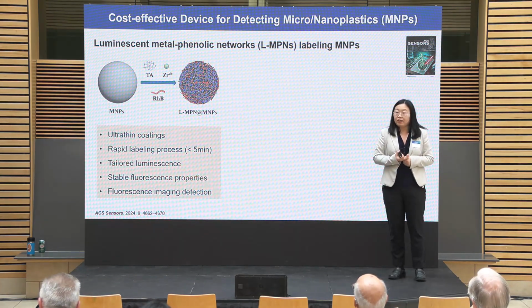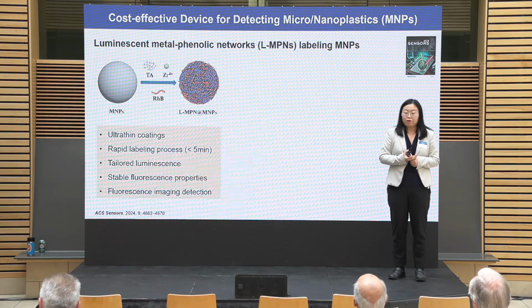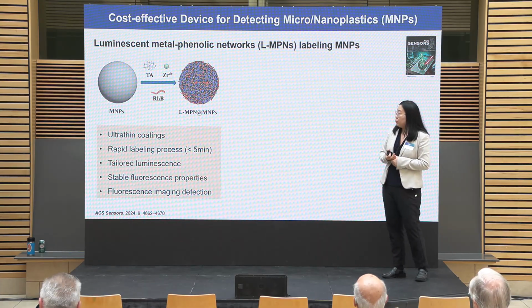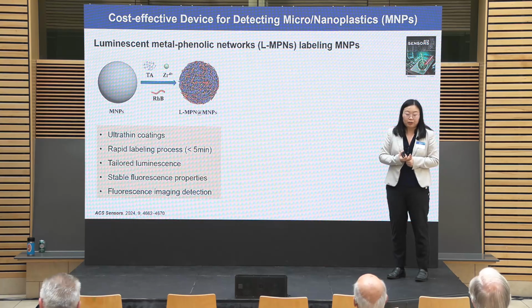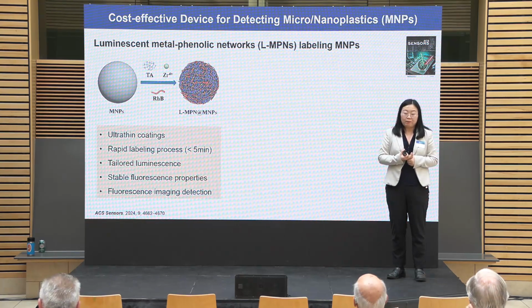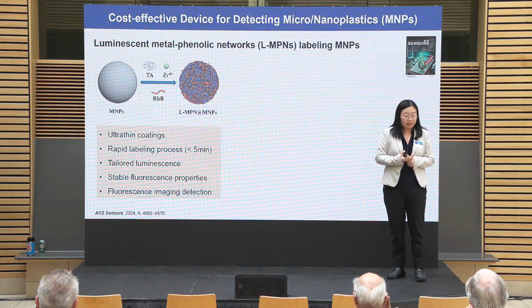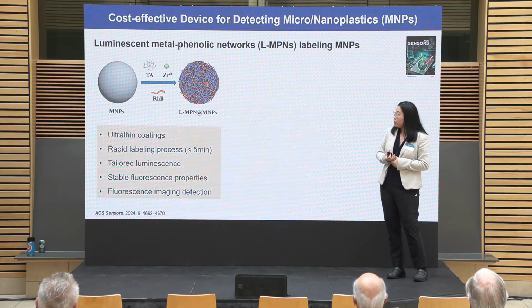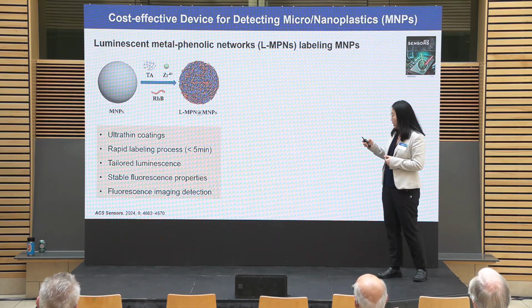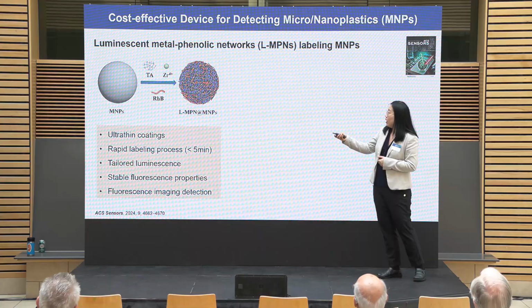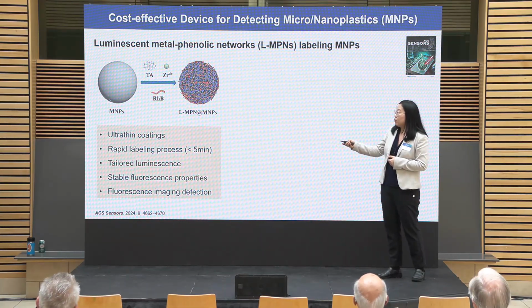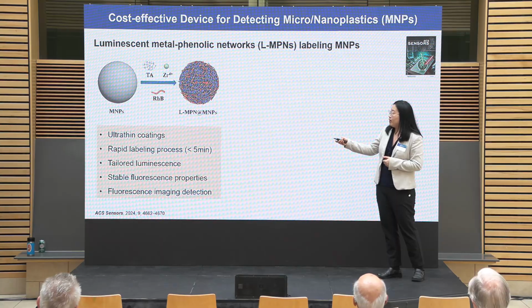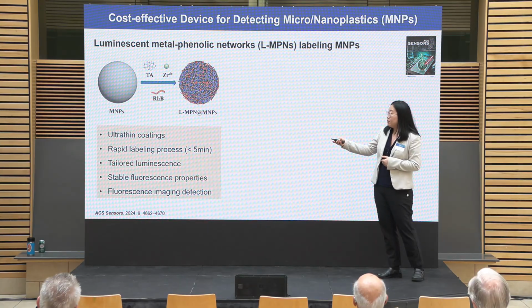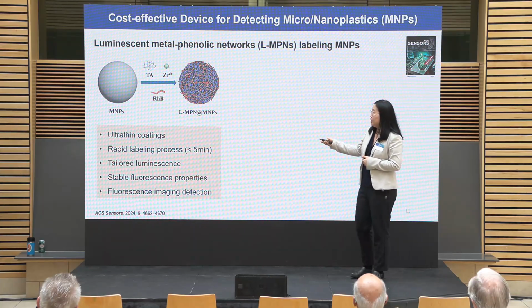So in our lab, we developed a portable device for the detection of micro and nanoplastics. We use a novel luminescent metal phenolic network, which we also call LMPN, to label micro and nanoplastics. Metal phenolic networks are the coordination between metal ions and phenolic compounds. Those networks can further interact with luminescent dyes, for example, rhodamine B, to self-assemble into coating layers onto the plastic surface.